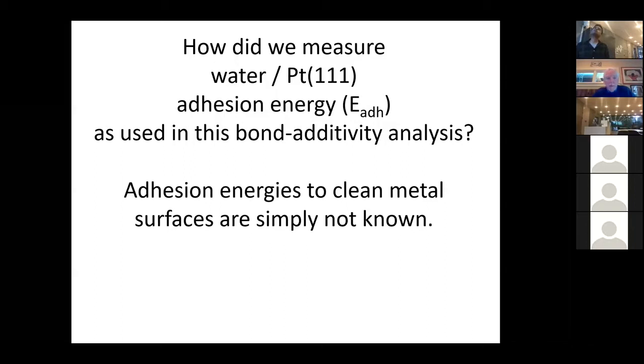I have to say it's a good question, because that's what I thought at first was going to be the explanation for why the heat of adsorption was so low in aqueous phase compared to gas phase, that surely the phenol must be taking on a totally different geometry. But I think what this bond additivity model proves is that it's not the case. I think that the phenol in aqueous phase, according to the thermodynamics that I just went through, could very well have almost the same kind of nature of binding as in the gas phase or in ultra high vacuum.